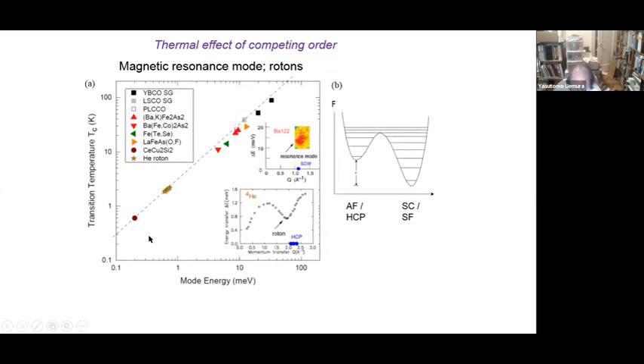And so in my opinion, this is suggesting that thermodynamically, probably this excitable mode of the competing state is determining Tc. In fact, the resonance mode appears in the periodicity of the competing antiferromagnetic order. This is very similar to the rotons appearing in the periodicity of the solid. And in the free energy diagram, there are two competing states, and the resonance mode-like energy is, I think, corresponding to the difference between these two states. If, for example, magnetic order wins, then this energy comes down, and the resonance mode, the spin gap, is closed, right? So the spin gap is representing this free energy difference.